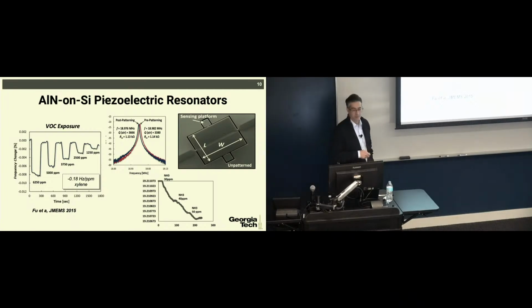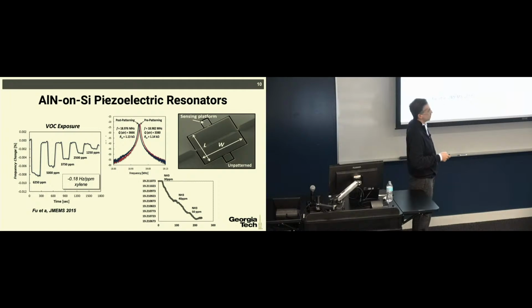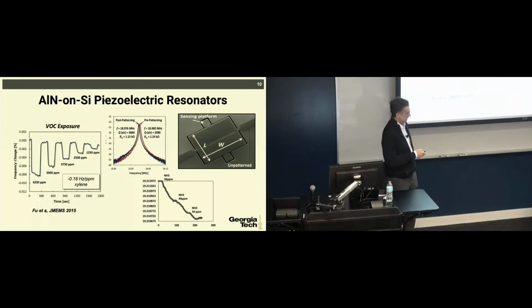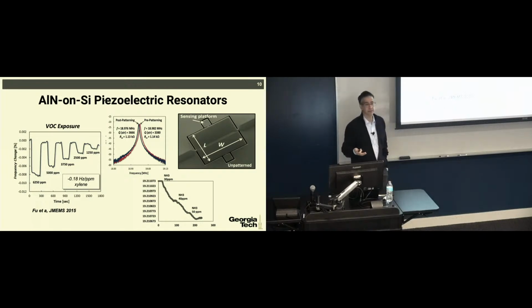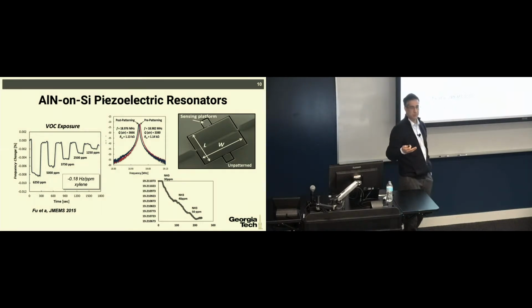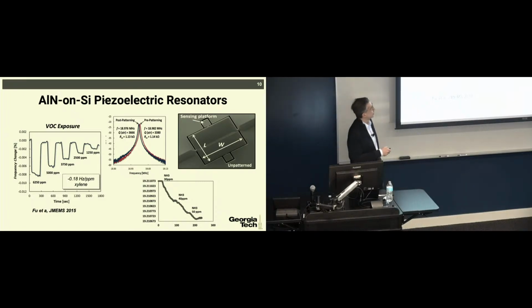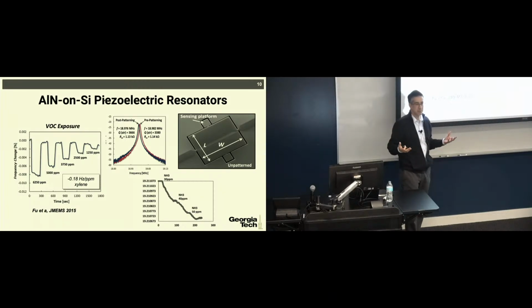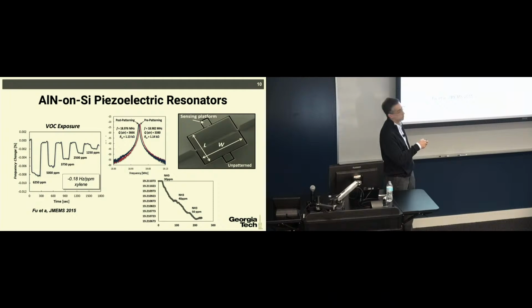And the nice thing about it was people found a way to just use a sputtering and deposit these piezoelectric films on silicon. So now you could use transducers, piezoelectric transducers on top of a silicon material and excite the resonance mode of the structure, and again, having different geometries to enable different functions. So for example, this device had these sensing platforms, like 2 platters at the end. And what you would do is that you would basically functionalize these 2 platters with some sort of a molecular recognition layer. So these will be sensitive to a certain type of molecules available in the environment. Once the molecules get absorbed on these surfaces, it will cause a change in the mass of the resonator, and then it will cause a change in the frequency, okay?